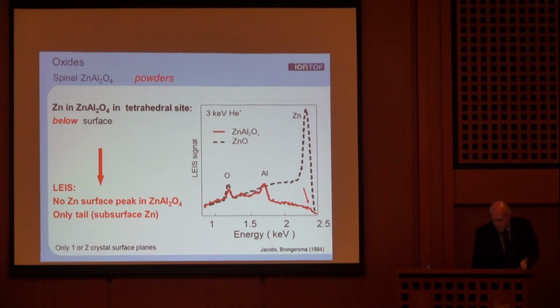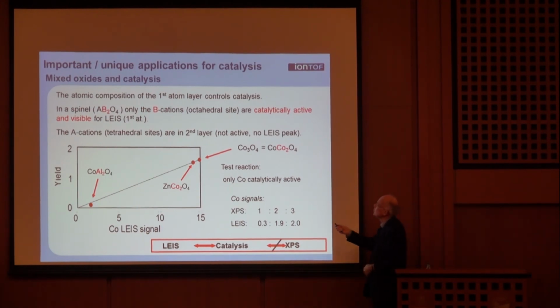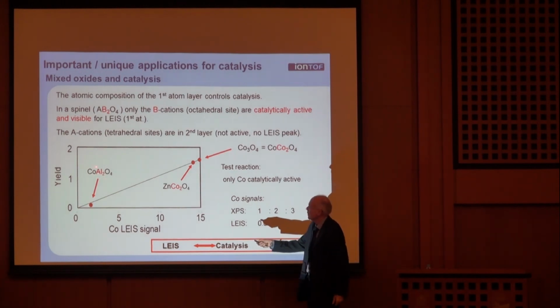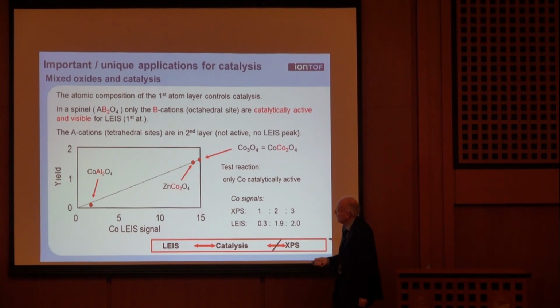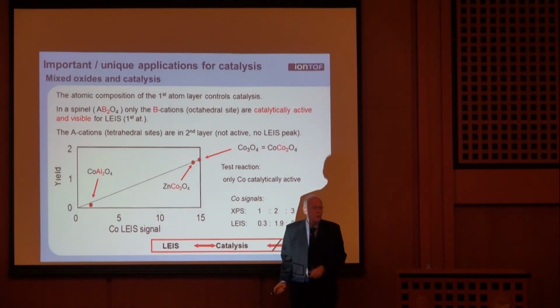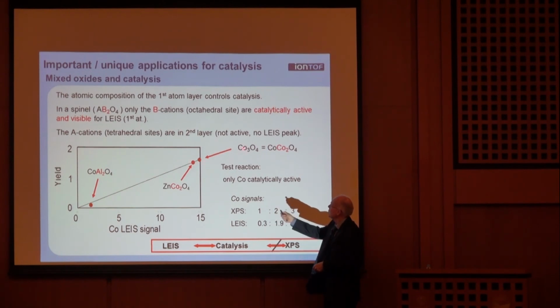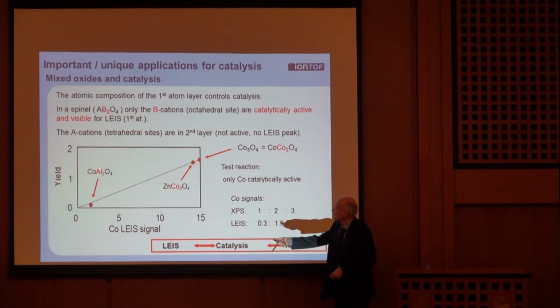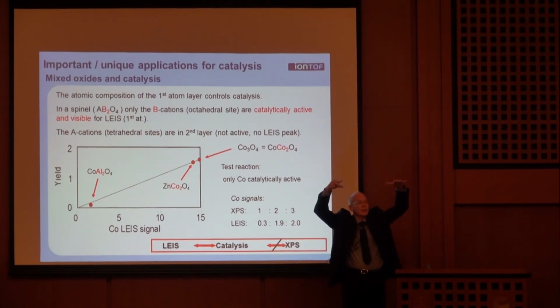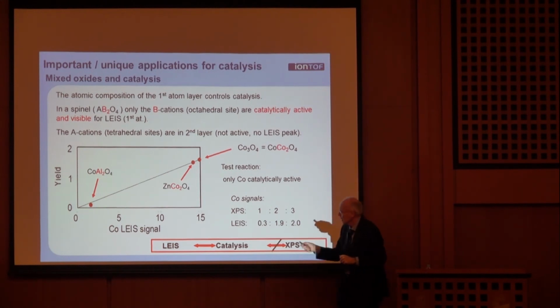Or if I take an example which is a little bit more important for catalysis, I show you things with cobalt. I have three different catalysts: cobalt aluminate, zinc cobaltate, and cobalt oxide. And you see that this is 1 cobalt, 2 cobalt, 3 cobalt. So you would think, I know what's going to happen. But here, there's almost no cobalt to be seen in ion scattering, and also the activity is almost 0. Here, there's a lot of activity, and it's the same as the 3. Why? Well, in red I have shown the elements that are at the surface, in black the ones that are just below. So that is why here there's no cobalt in the top layer, no activity. Here there are 2, and there are 2 as well, because the third one is below.